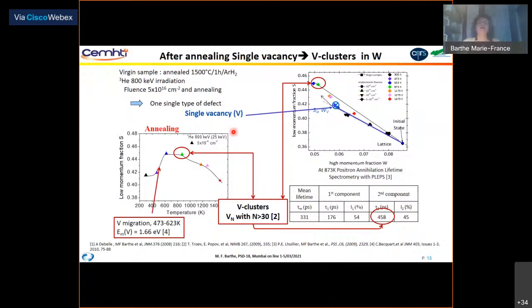And we anneal this sample, and you can see here the low momentum fraction S as a function of annealing temperature. You can see there is an increase in S, and if we go to S as a function of W here, we can see that when S increases, W decreases, and we have an increase of the slope. So we create some vacancy clusters, and this cluster formation is due to the migration of the single vacancy, which appears